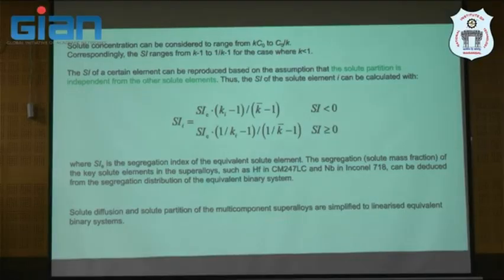And this is what we call the segregation index. If it's less than this, it will fall into this one. If more than this, it falls into this one. And then we identify the segregation profile specifically for CM247 based on our understanding from the experiment: hafnium is segregated in the grain boundary, and niobium for the Laves phase, which is decorated at the grain boundary as well.